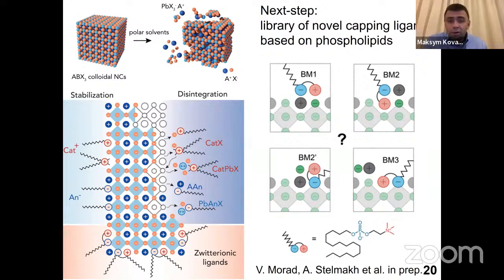And so then we thought, several years ago, how to run this ligand functionalization in a rather softer manner, and yet bind our ligands even stronger. So we came a few years ago to the idea to use zwitterionic ligands, where you have a positively and a negatively charged group in one molecule. And so now this group will attach to the surface by displacing a pair of cation and anion at the surface. And that worked. One example is lecithin. It's a natural phospholipid. You find it in chocolate and in many other products, very cheap. It works wonderfully.